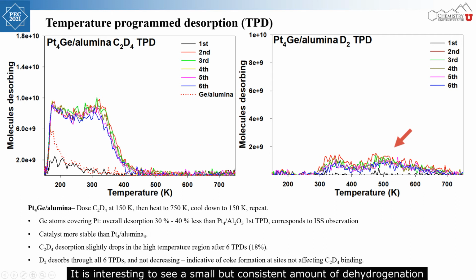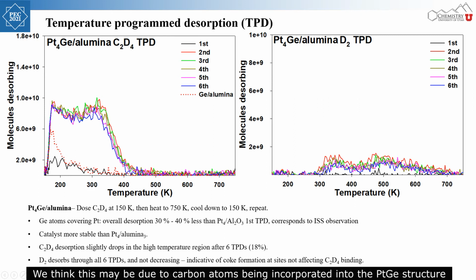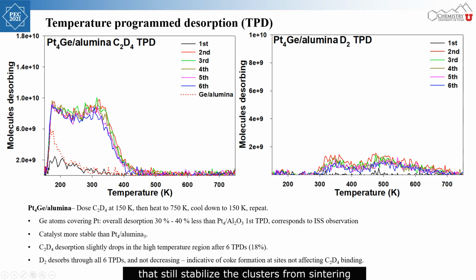It is interesting to see a small but consistent amount of dehydrogenation that should lead to coking, but somehow the coke did not affect C2D4 desorption. We think this may be due to carbon atoms being incorporated into the platinum-germanium structure that still stabilize the clusters from sintering, while maintaining the number of sites for ethylene binding.